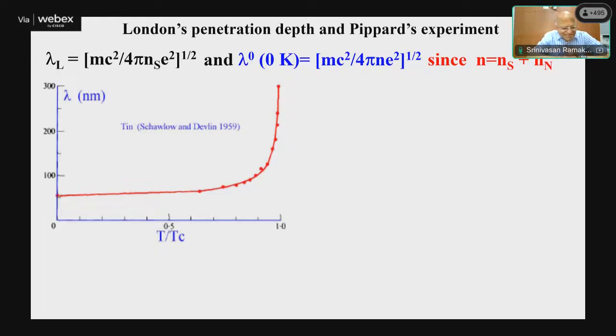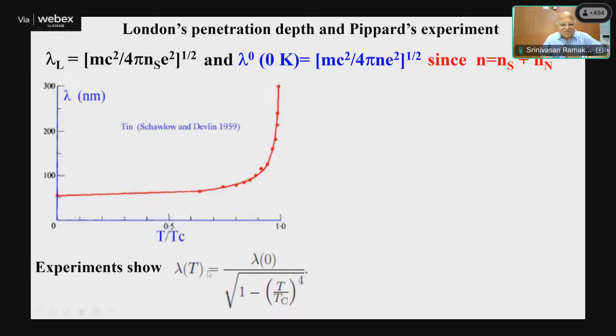And there was one great experimentalist called Pippard. He was trying to do the experiment. London gave a theory, right? He gave this penetration depth as this fraction. This is the superfluid density, and these are all standard: c is the velocity of light, m is the electron mass, e is the charge, and so on. So he decided to measure a standard system like tin. It was measured later by Devlin, who measured lambda as a function of temperature T by Tc. You see there is a nice variation and it diverges close to Tc as expected, because then there will be a full penetration when it goes to a normal state. This was the experiment which showed how lambda behaves as a function of temperature.